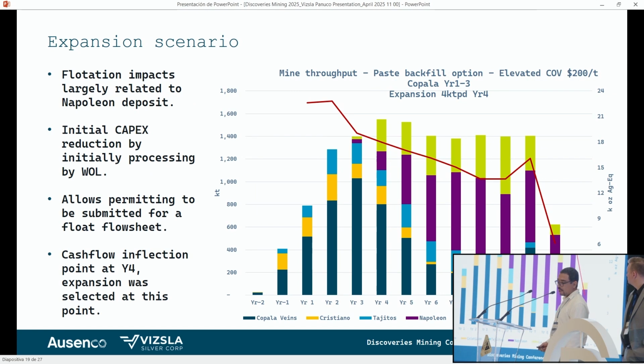So 70 microns is the optimum size for this process. As you can see right here, first there's the Copala deposit early on in the first years of development, and then the Napoleon deposit starts being the predominant deposit. As we saw on the previous slides, the Napoleon deposit responds pretty well to flotation, so it makes sense to have a flotation expansion at year 4 to process the Napoleon deposit and have some higher recoveries on this.